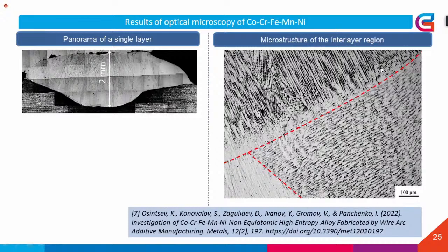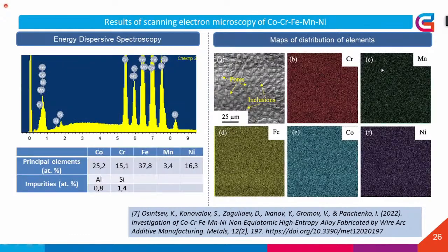For another alloy, cobalt-chromium-iron-manganese-nickel, it is visible that depending on the layers of the material, we can see the division of the contacts, and the grain orientation is changing due to different thermal cycles, heating and cooling. Consequently, the orientation is changed. As well as that, unfortunately, the wires were not purely clean. There were some mixes that we cannot, unfortunately, avoid in the production.